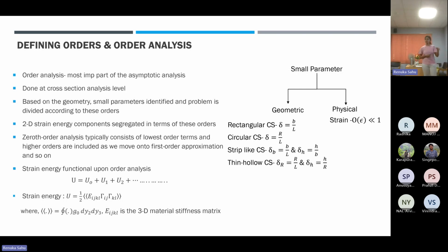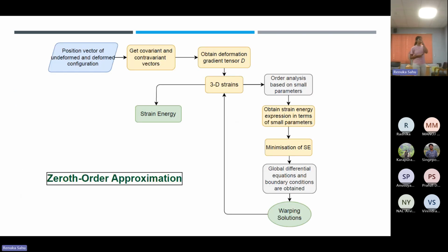Then moving further for first order approximations, we can consider U0 plus U1 and minimize those to get a variational formulation. So this is the whole flowchart explaining the zeroth order approximation, wherein you start with the position vectors, you get the covariant and contravariant vectors, and you obtain the deformation gradient tensor. Once you get the deformation gradient tensor, it is used to get the 3D strains, and order analysis is done based on small parameters.